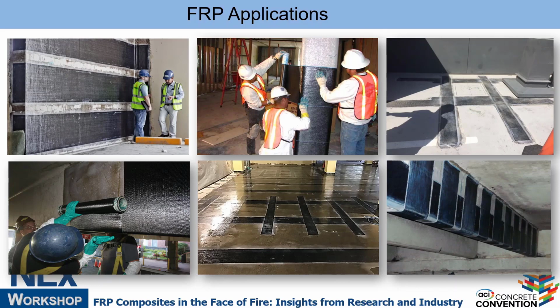A lot of applications, right? That's why we're talking about it, because 20 some years ago it was considered new technology, even though it started almost 40 years ago. Development and research in FRP in the 70s, where you can see that. Now we do them for seismic strengthening for walls. We wrap columns to increase ductility, shear strength, axial load, and use them around penetrations. So this slab is planned to be cut, maybe for a new duct going through it. So they put just FRP to reinforce around this penetration to control the cracking and make up for any loss of steel, shear strengthening of beams and columns by wrapping. FRP can be on the top side of the slabs, on the underside of the slab. So they're all different configurations.